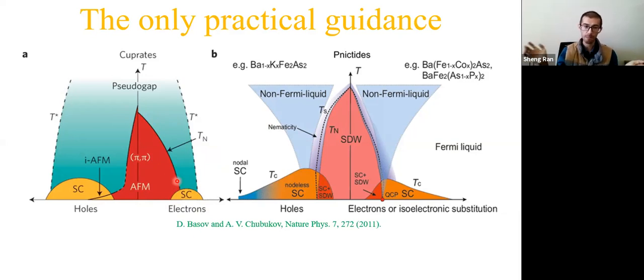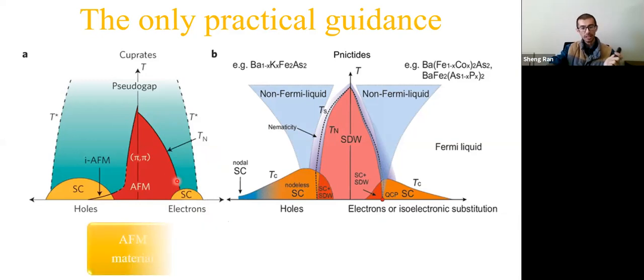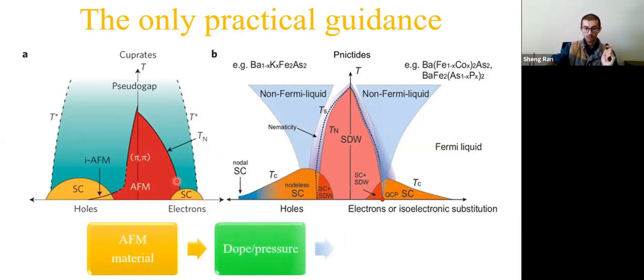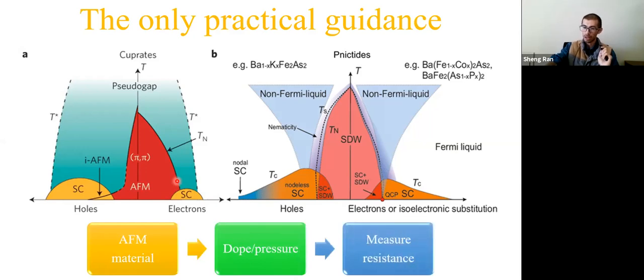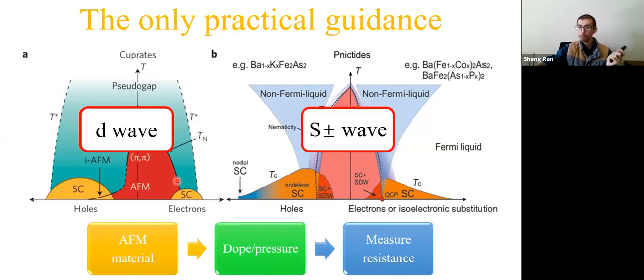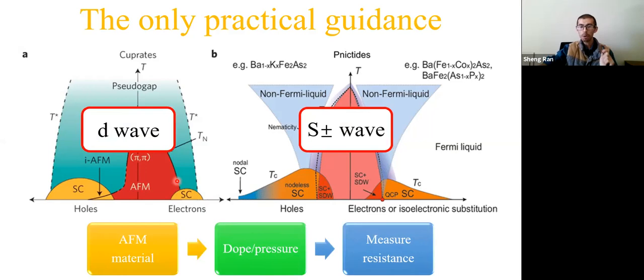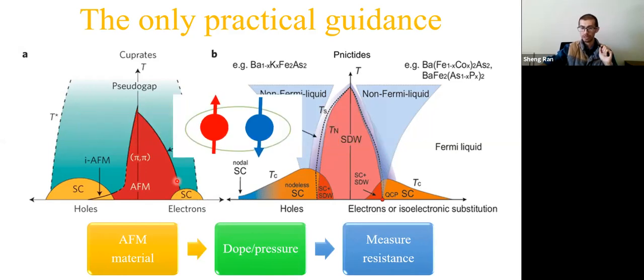Actually, during my PhD, I devoted a lot of time on this. So the idea is get an antiferromagnetic compound, try chemical substitution or apply pressure, and just measure resistance. If it's not a superconductor, try another one. But this will not help us to find a triplet superconductor, because we know cuprate is d-wave, iron pnictide is s plus-minus wave, both are spin singlet.